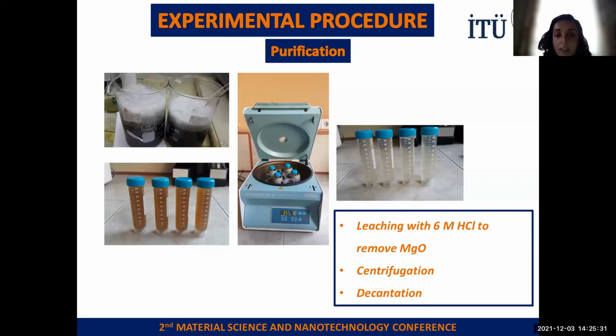the prepared powders were taken from the milling vials, and they need purification, because, if you remember, magnesium oxide is the byproduct of the synthesis reactions. So magnesium oxide can be removed using hydrochloric acid leaching. After the mechanochemical synthesis, these powders were leached using 6 molar hydrochloric acid, waiting in the acidic solution, and then they were centrifuged and decanted to purify the synthesized powders.